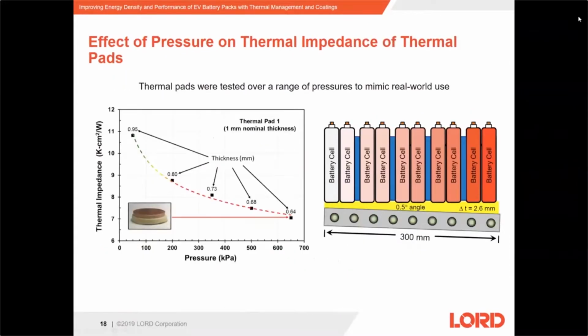Here, we examine the effect of pressure on the thermal impedance of the thermal pads. The x-axis measures pressure ranging from 50 to 650 kilopascals, and then thermal impedance is measured on the y-axis as a function of pressure. As you can see, a significant amount of pressure had to be applied to lower the thermal impedance of these thermal pads. In our experiment, whenever that significant amount of pressure was applied, we actually saw the pad squeeze out of the TIM tester, as evidenced by the picture in the bottom left corner of the graph.